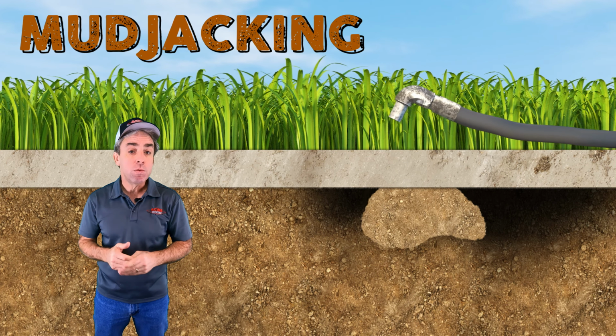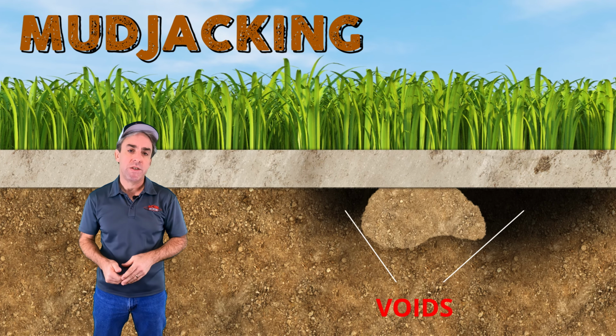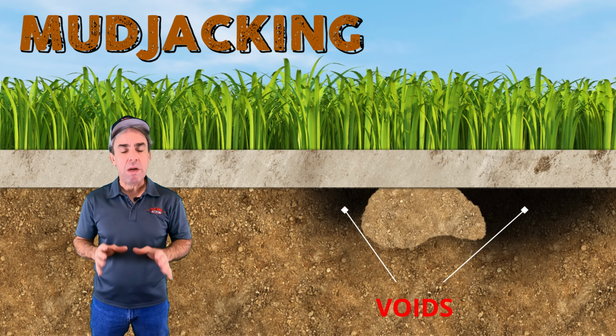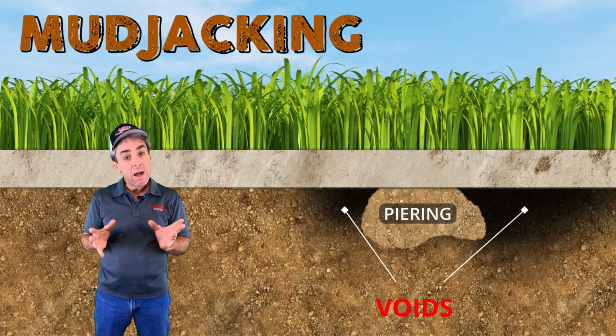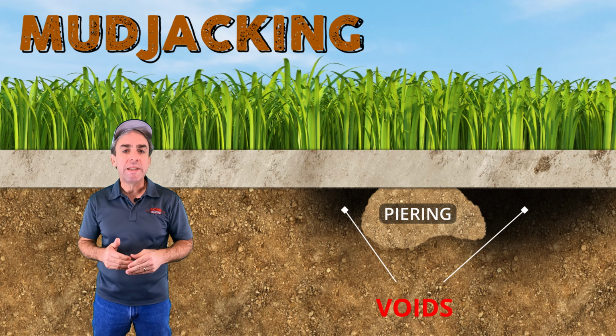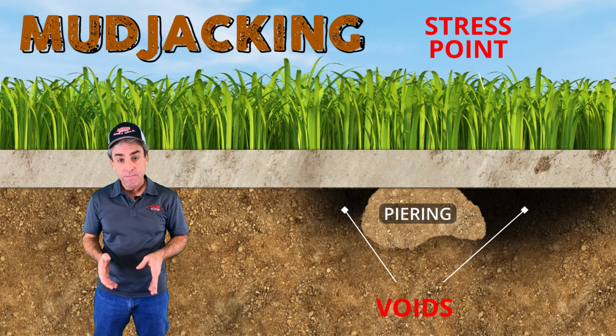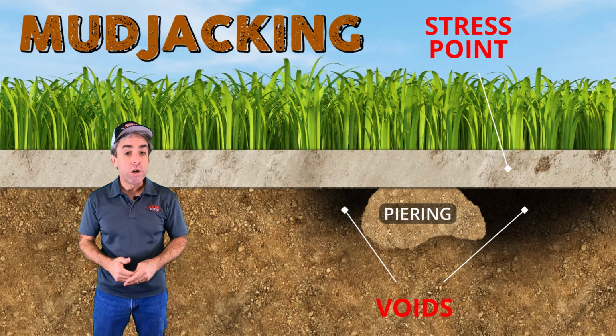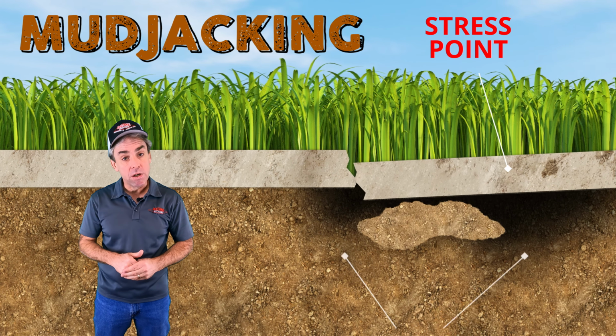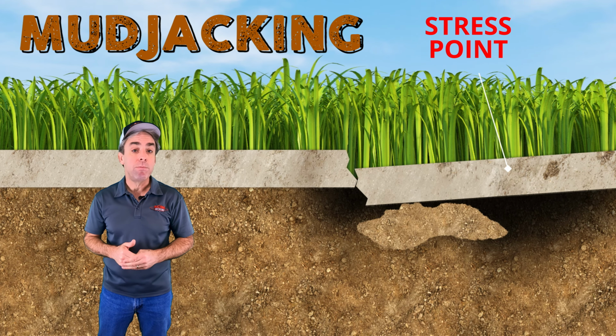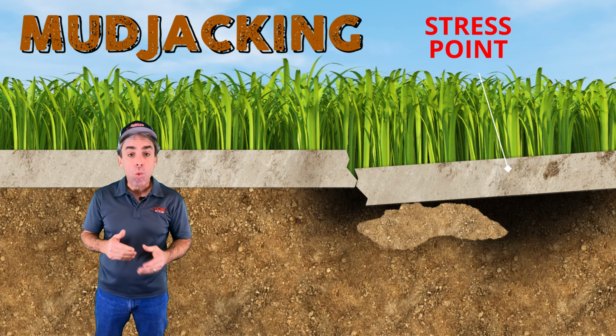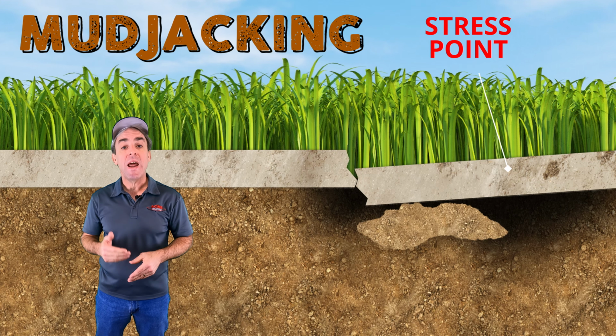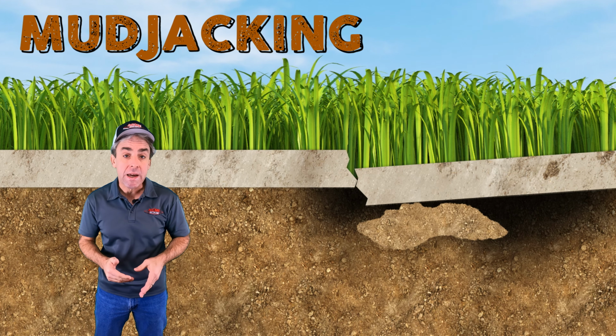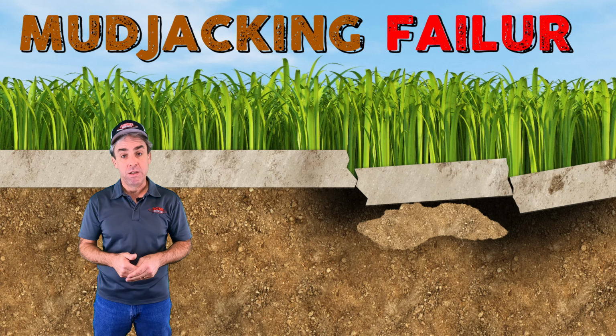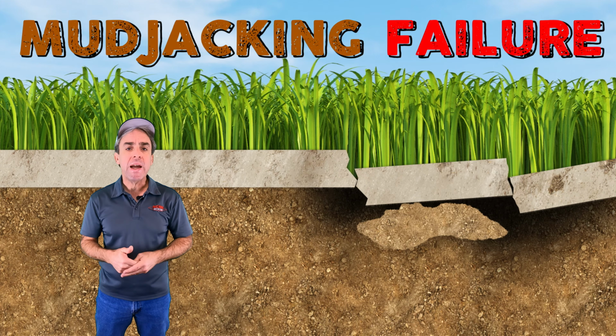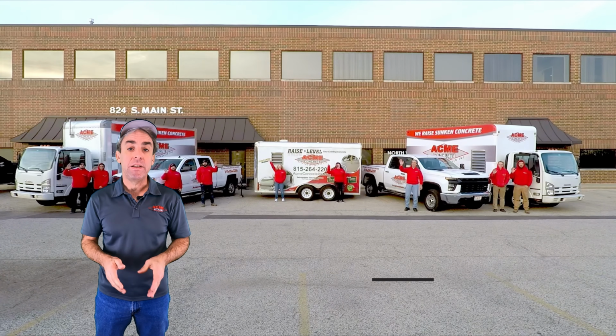Unfortunately, its lack of spread results in voids. We refer to this as piering. The concrete is raised, but the lack of support can leave the slab stressed. Over time, moisture can soften the mudjacking material, resulting in the slab dropping again. What's even worse is that the lack of support can actually result in the slab cracking and require replacement at this point. With Acme, our material is highly flowable.